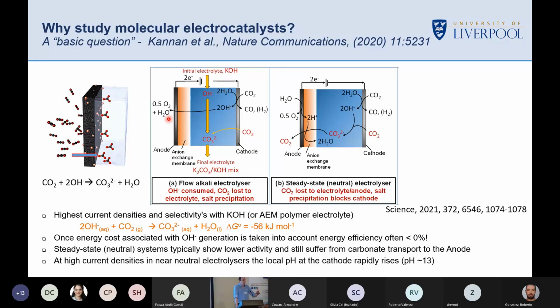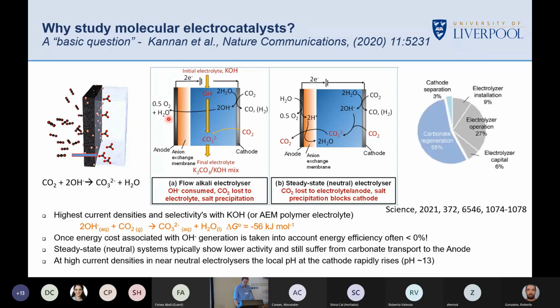So I've got this wonderfully designed gas diffusion electrode. There's fantastic science going into modifying these to control the wetting of these, to control the gas diffusion, and then I might get salt crystals in them. And then the device will fail. And that's one of the big causes of device failure. So we really want to avoid carbonate if we can do this at all.